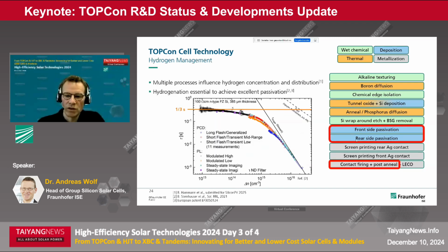Now, looking a little bit into the passivation sequence here, we saw that hydrogen management is an essential part to achieve high efficiencies. There are multiple processes that affect the hydrogen incorporation and distribution. Of course, the passivation layers introduce hydrogen, but they also might serve as a diffusion barrier. And then during contact formation and post-anneal, you have the redistribution of hydrogen, and it's very essential to balance these processes carefully to achieve a good hydrogenation of the interfaces and also the bulk.